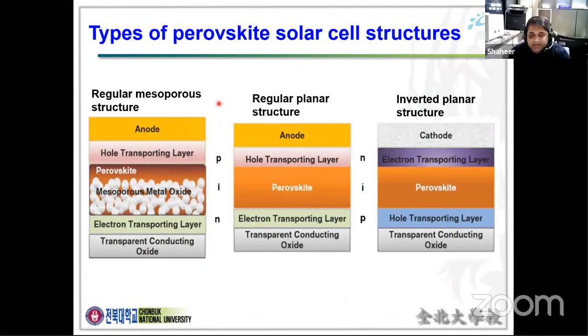So far, there are three kinds of perovskite solar cells. One is what we call the mesoscopic structure, the planar structure of the perovskite solar cells, and the inverted. The difference between the three is, in the case of the mesoporous structure, we usually use this kind of mesoporous metal oxide layer, which has many mesopores on the surface, which is helpful for absorbing the perovskite layer.